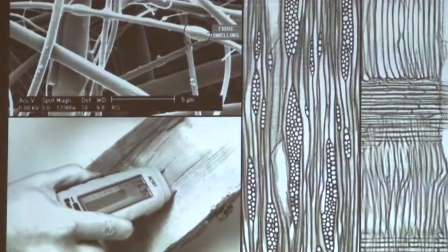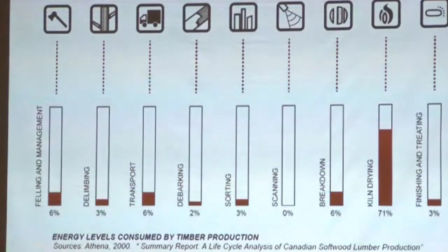As probably all of you know, wood is called a hygroscopic material, which means it maintains its moisture content in equilibrium with the surrounding relative humidity. And the related processes of adsorbing and desorbing water molecules affect the microfibrillar structure, which results in both a change in strength and a differential change of dimension. Usually, we experience this dimensional instability of wood as a deficiency, because we have jammed drawers or wobbly parquet floors, and one could argue that we have about 4,000 years of craftsmanship to avoid wood doing what it always wants to do, and that is swelling and shrinking. In fact, we invest more than 70% of the energy in wood processing to suppress this materially inherent behavior, which you can see here.